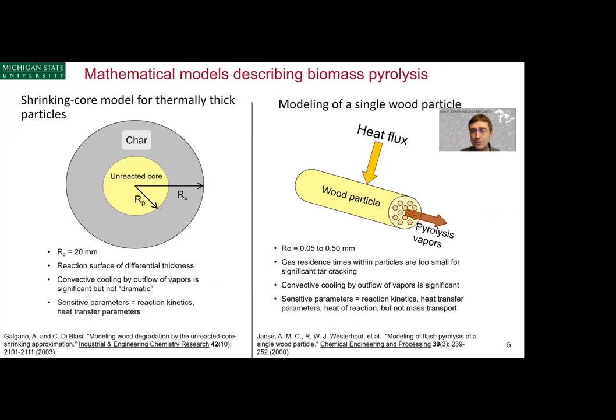This leads to one reason you might choose fast pyrolysis versus slow pyrolysis if your aim is to make liquids. There's a smaller amount of time for cracking reactions involving the metal catalysts embedded in the char to occur if you have very small particles. Results like that are important because they inform our ability to design better reactors.